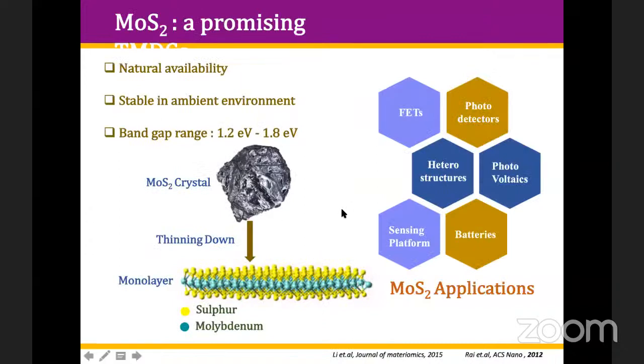So out of these 2D materials which we have listed, there are a number of 2D materials. Which material is the promising one? MoS2 seems to be the most promising material, but not limited to MoS2; there are other materials also. But in my view, MoS2 seems to be the most promising because it is naturally available. It is stable in the environment and you can tune the band gap from 1.2 electron volt to 1.8 electron volt depending upon the thickness, from monolayer to 10 layers of the system.